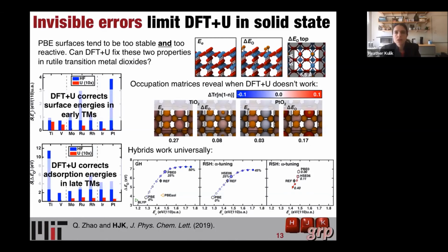And for instance, we were interested in catalytic properties, and what you would typically find is that using the wrong U by about 1 electron volt, so use a U of 4 when you meant to use a U of 5, would only change the property we were interested in by about 0.1 eV. So compared to the error in the original PBE functional, it's okay often to use a Hubbard U that's off by about 1 eV, and it's not going to dramatically change your properties. Other properties could be more sensitive. I think I just basically made the case that band gaps shouldn't shift more than 0.25 eV per eV of U. So similar things in play.